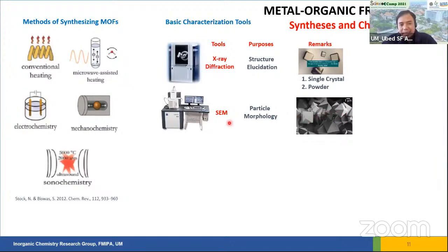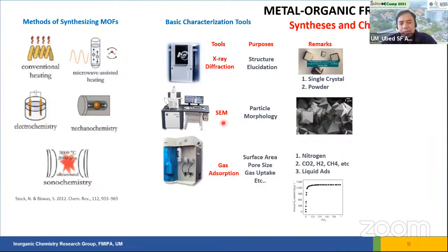This is called scanning electron microscopy. The third one is gas adsorption. This is also important since the metal organic framework is a porous material. For gas adsorption, for example, we can use nitrogen and carbon dioxide. We can determine the surface area of the MOF, and also the pore size.